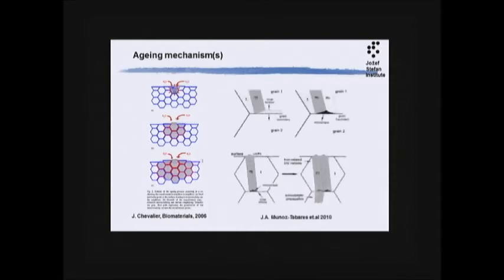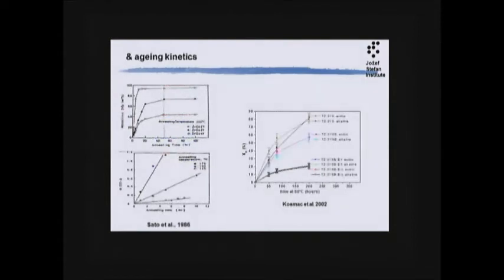Later on, people discovered it's more complicated, and I'm afraid it's even more complicated because we have these phase separations. We never know what's where. And the monoclinic will twin, because if the volume is getting bigger, then the material wants to accommodate. It does it by twinning, and that will lead to a texture. The microcracks will not be statistically or randomly oriented, but they have a preferential orientation along the surface, basically. What you will see also from the X-rays.